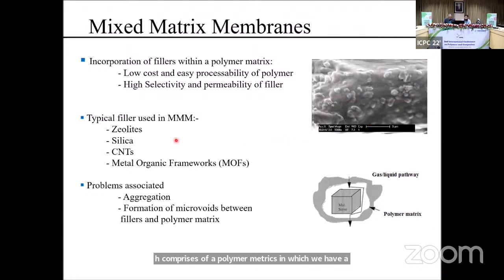A number of different fillers have been previously used, such as zeolites, silica, carbon nanotubes, and metal organic frameworks. However, the major problem with the commercialization of mixed matrix membranes is that there are certain problems associated with the dispersion of fillers in polymer matrices. Because polymer is an organic part, and these silica and zeolites are inorganic, they don't really like each other. As a result, usually there is a micro-void or a space generated between an inorganic filler and a polymer matrix, and because of these gaps, the selectivity or the separation of the membrane reduces because the non-desirable gas also passes through this gap.